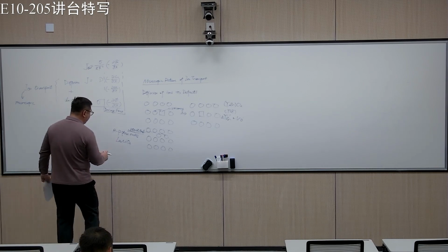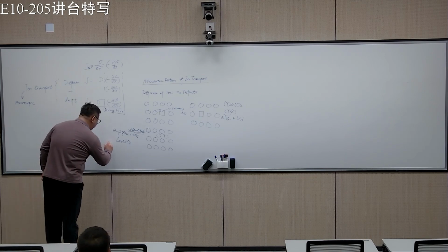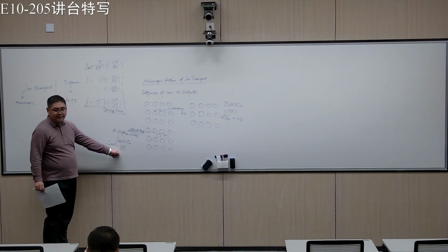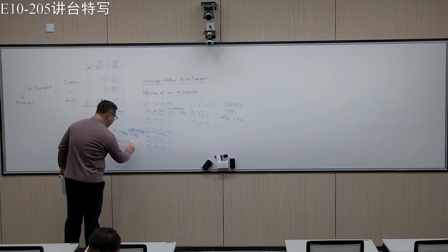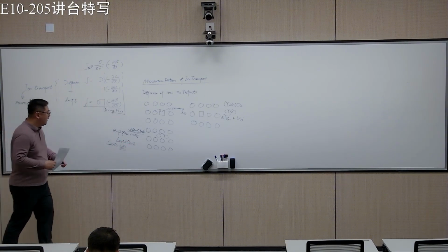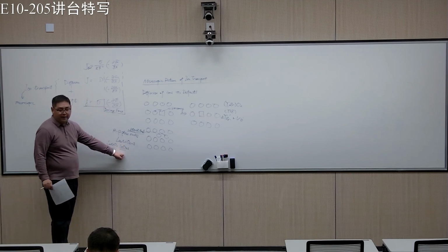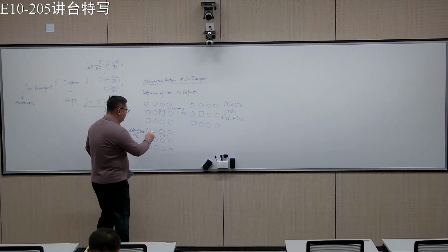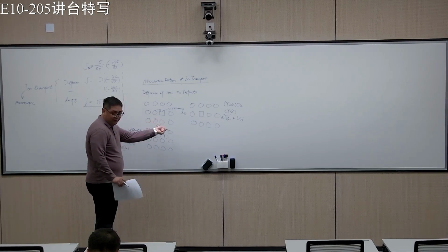One way to think of it is that you have one layer of perovskite, then another layer of rock salt. The rock salt layer is basically the lanthanum oxide. Okay. So you can have oxygen over-stoichiometry in this rock salt layer. Then you have, for example, these oxygen interstitials, then you can really jump.